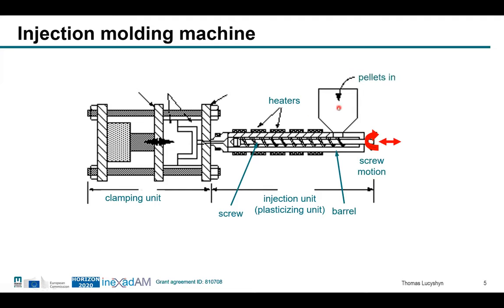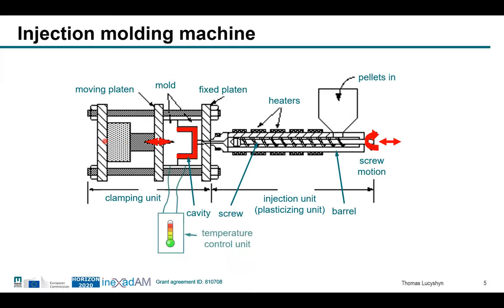The pellets are going in through the hopper, can either be manually, just push it in here, or you have some pneumatic conveyor system where automatically the pellets are transported into the machine. The clamping unit mainly consists of a fixed machine platen and a moving machine platen, and onto these two platens the mold is fixed, which consists of two mold halves which are forming the cavity. And additionally, the moving platen can, as the name says, move forward and backward to open and close the mold. So once the part is shaped and cooled down, the mold is moved backward, and then the part can be demolded. Additionally, we also need some temperature control unit to control the temperature of the mold.